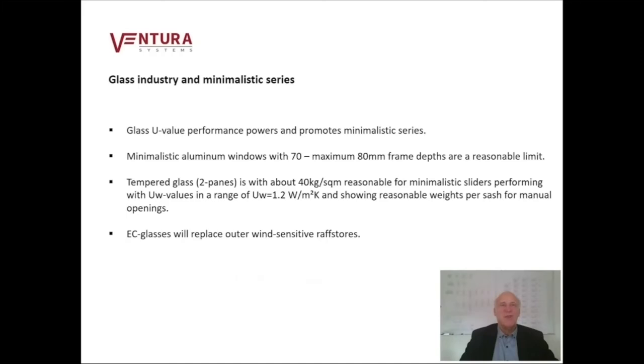Minimalistic aluminum windows will have a reasonable frame depth of the outer profile from 70 to 80mm. That is a limit which is given for the future. Tempered glass, 2 panes with a weight of about 40 kg per square meter, are reasonable for minimalistic sliders. We can expect UW values of good systems in the range of 1.2, so that is quite reasonable. And the weight of the systems enables manual opening.